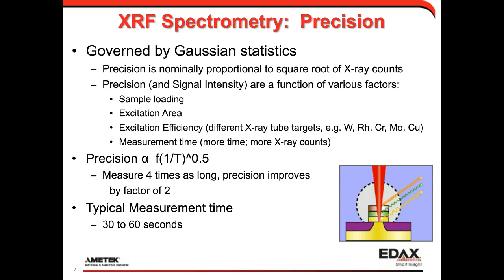Signal counts, and therefore precision, are affected by various factors like sample loading. The more sample you have, the more concentrated or the thicker the coating is, the more signal you'll have. The more excitation area you have, the more signal you'll have. Sometimes we can use different sorts of X-ray tubes to get a better efficiency for a specific measurement, and we take that into account when we're putting together a system for specific applications.